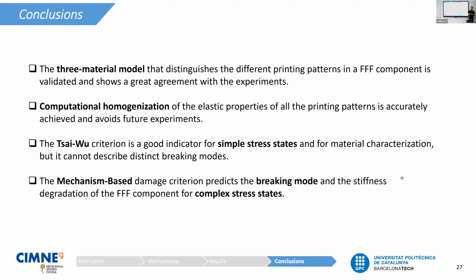and it's normal that it's used in a standard way in the industry, but it's only a good indicator for simple stress states. When you use it for more complex stress states, where shear, normal stresses, and other special combinations appear, it is not a good indicator and fails to capture the failure mode. While the mechanism-based damage criterion correctly predicts the breaking mode and is more appropriate for complex stress states.